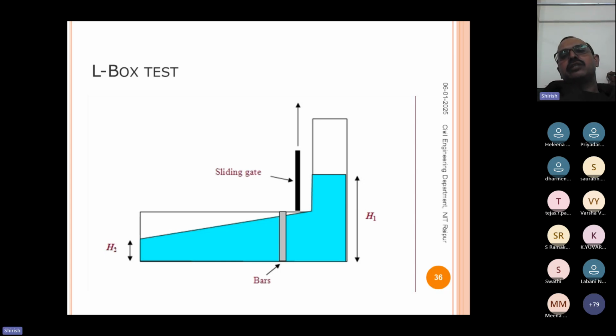This is the L-box test. In the L-box test, on the right hand side, we pour the concrete into this L-box and then the sliding gate is lifted. Now, if the concrete is very workable, H1 will be nearly equal to H2. That is a very good quality of concrete which can pass through the reinforcement. Here you can see there are bars, and the concrete will flow through these bars. If it is very workable, H1 will be very close to H2. The ratio has to be 0.8, meaning H2 should be at least 0.8 times H1. That is what is required.